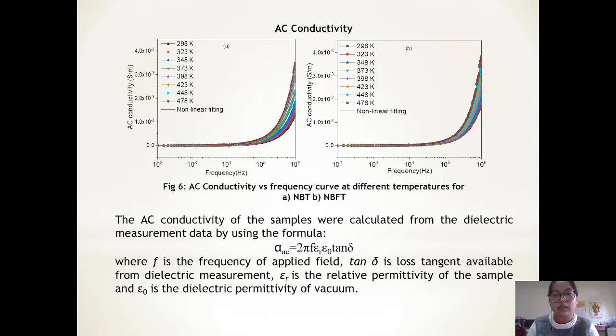We can also see that the AC conductivity of the iron-doped sample is slightly more than that of the pure NBT. This may be due to the fact that oxygen vacancies are created when iron is substituted in place of titanium in order to maintain the charge neutrality.